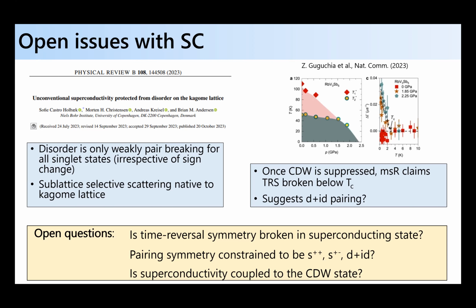Sorry, I didn't quite follow what special property of the kagome lattice means that disorder won't break sign-changing order parameters. I tried digesting this paper. I think it has to do with the phase space that you can scatter to, because the wave function is sort of localized on one site. Evidently, when they calculated it, they basically said that all disorder is equivalently pair breaking for all singlet states. The same argument didn't apply to triplet states, for instance. But here's the reference. So they're just saying that in the absence of strong pair breaking effects, it could possibly be measured.